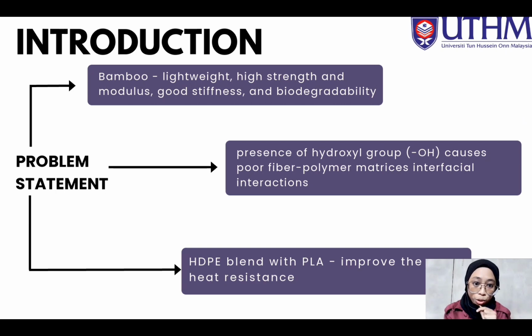Okay, next is the problem statement. In this study, I will use bamboo as my sample to test the polymer blends. Bamboo is lightweight, with high strength and modulus, good stiffness and biodegradability. Since this bamboo is not treated with pre-treatment, it has poor fiber-polymer matrix interfacial interaction because of the presence of hydroxyl groups. So to improve the interfacial interaction, we will treat the bamboo fiber and blend it with PLA HDPE to improve the heat resistance and also flexural strength.